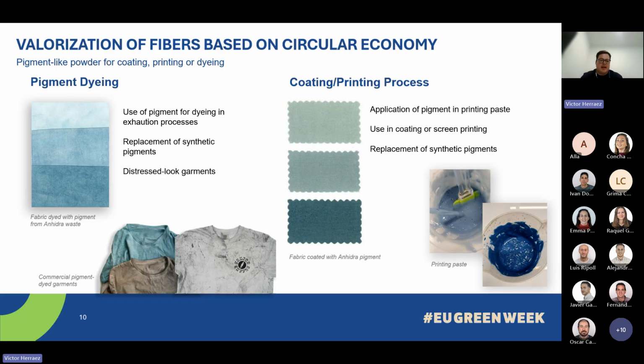So for pigment dyeing, we've worked mainly with cotton substrates. So we had to pre-treat these fabrics with, in this case, an ammonium quaternary polymer. So this fabric can bind with the pigment, and then we can dye fabrics, and we get these distressed looks that can be put into the market.